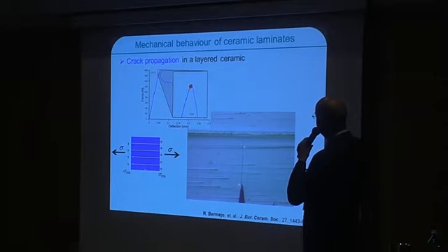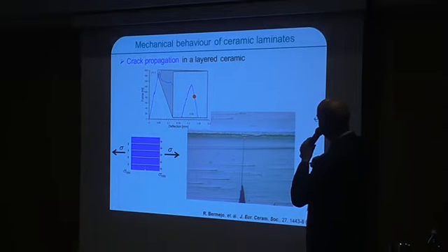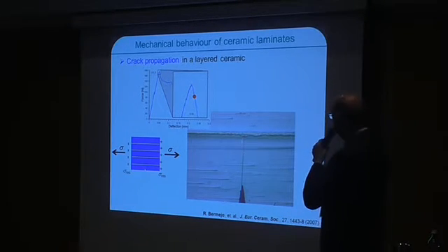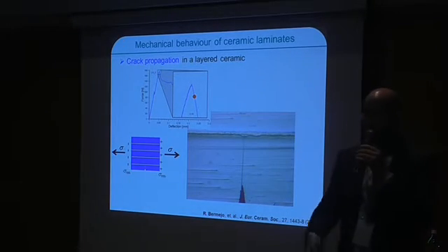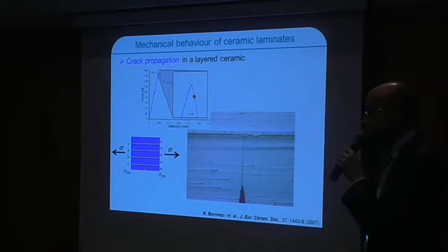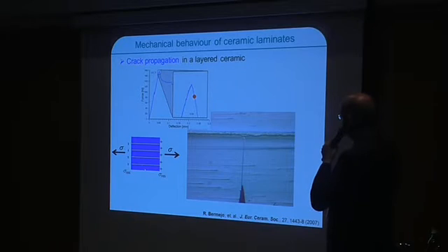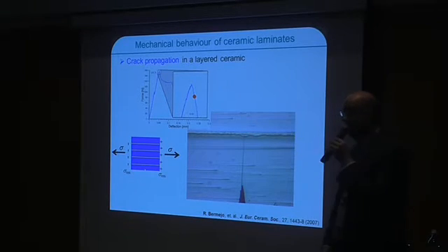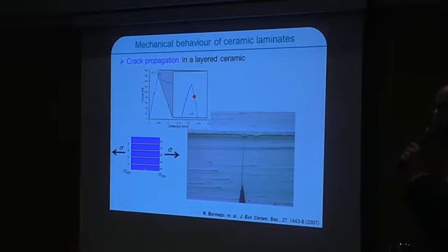You will see a crack popping in and arresting here, and this is the second video where we overcome this point here. We can see that the crack, due to the compressive stresses, will not propagate straight through, but it will bifurcate in the compressive layer. My colleague Olga was modeling yesterday the stress and energy conditions that you need to have this bifurcation. So residual stresses are important, thickness of the layer, etc.